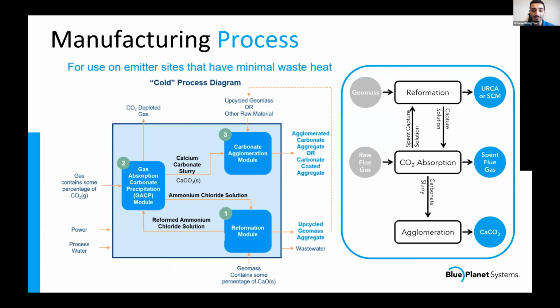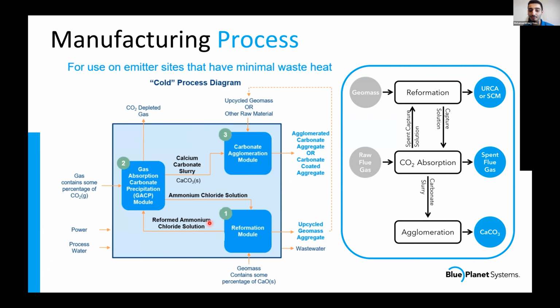And so here's our process a little more. I'm going to start off, let me see if I can get my pointer up. I'm going to start off here with this reformation module. This reformation module is what I was mentioning earlier, which is the acid wash. We're getting this ammonium chloride solution, which is an acid, in contact with geomass, which is what we term our upcycled, demolished and returned concrete or other industrial waste. Once it comes in, we get it in contact with one another. You're left with this upcycled material and wastewater. That solution is now an alkaline solution, which then goes into the CO2 absorption column.